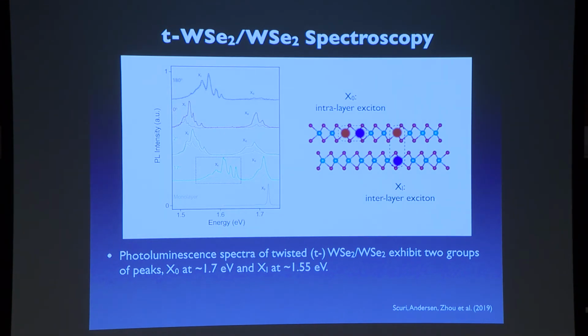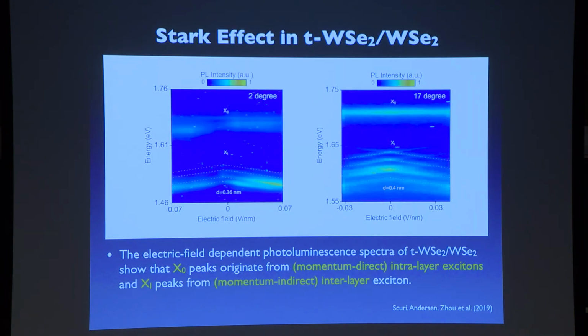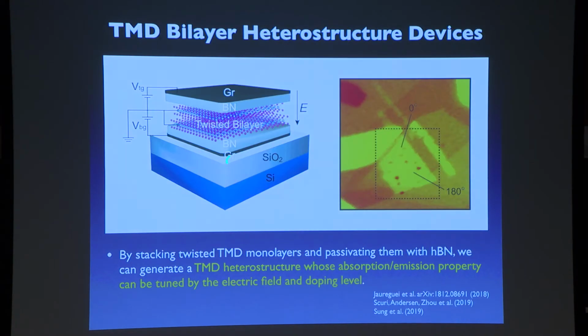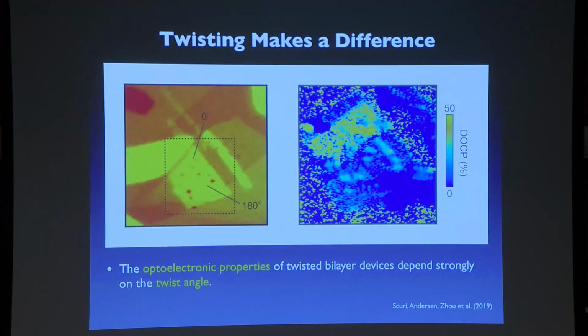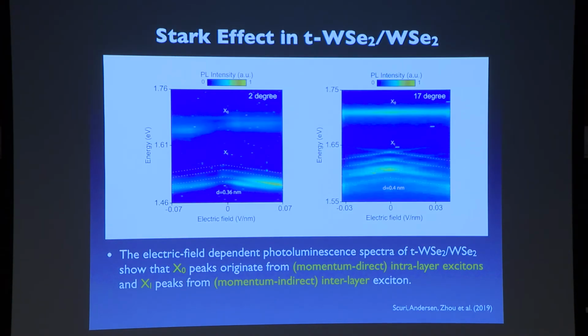How do you assign which one to which? You can do so by measuring the so-called Stark spectrum, by applying an electric field and seeing how those lines shift. So what we are doing, in this particular geometry, is applying the voltage between the two graphene layers so that we can apply an electric field perpendicular to the plane of those atomically thin semiconductors. And then what we are measuring is the position of the peaks. These peaks do not shift as a function of the electric field. These peaks do shift as a function of the electric field.